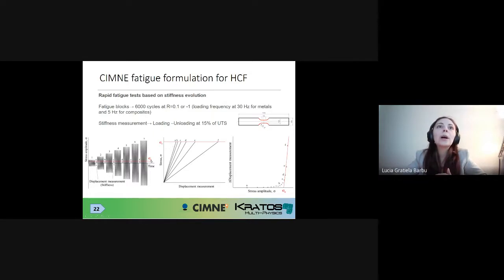And as you finish a block and then you check this change in the stiffness, you can see here that the displacement measurement varies after each load. So basically, if you quantify this change in the displacement measurement and plot it against the stress amplitude, you can detect here the fatigue limit of this specific material.